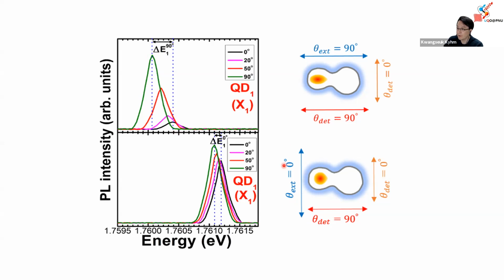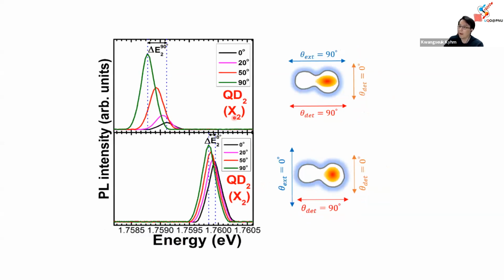However, in the case of 0 excitation, the shift is very small. So it's more circular, and it's more squeezed. And X2 also shows a similar feature. Large energy difference between 0 and 90 degree here, with the 0 excitation very small.